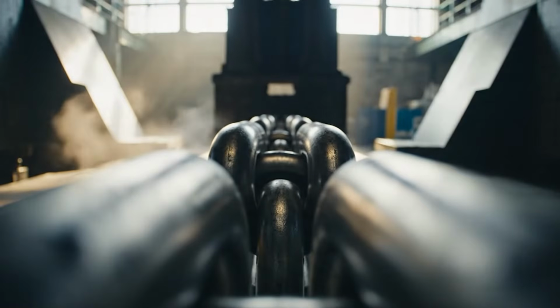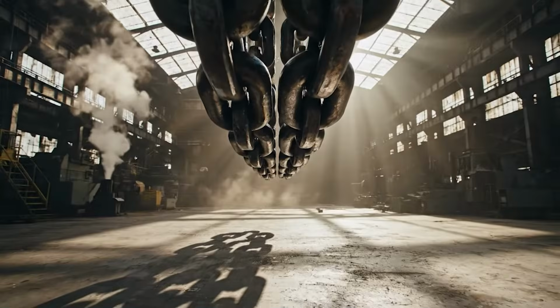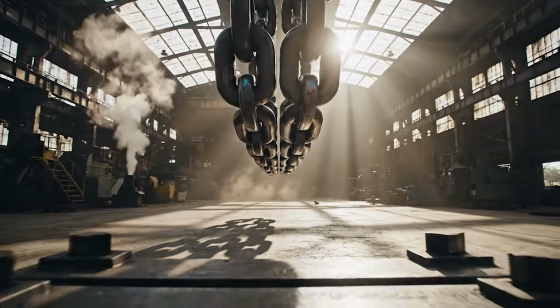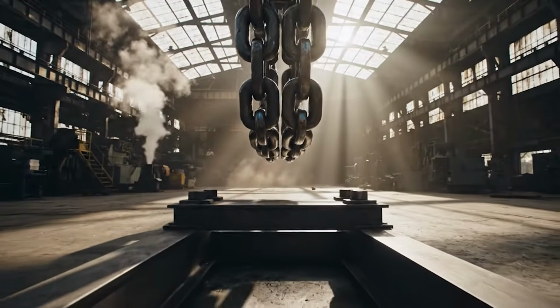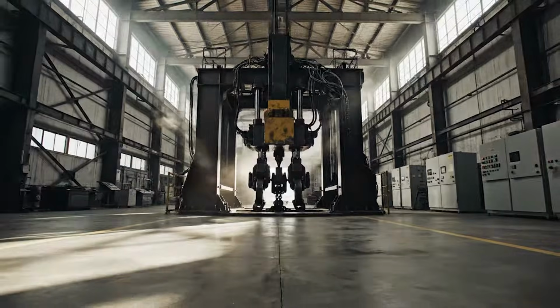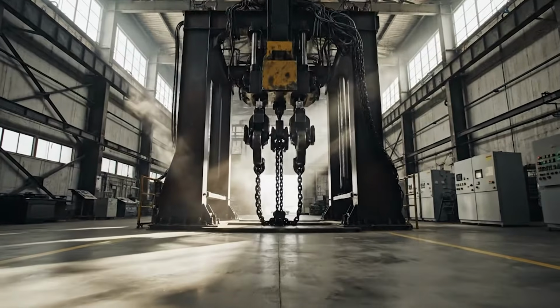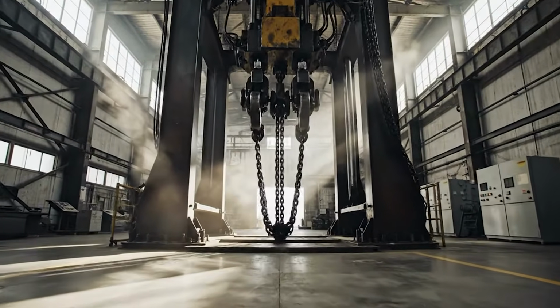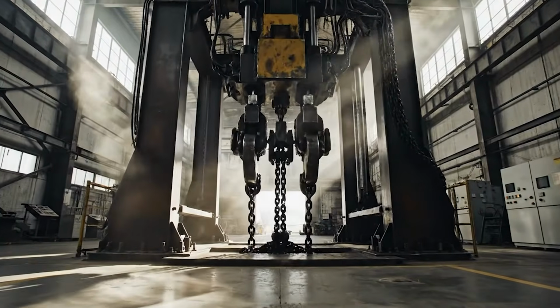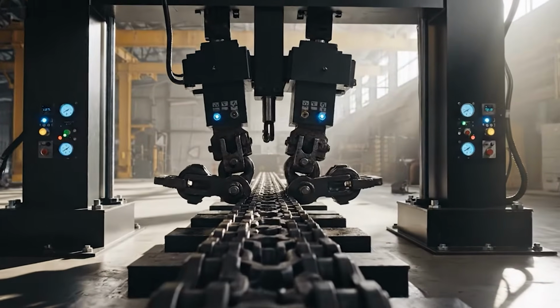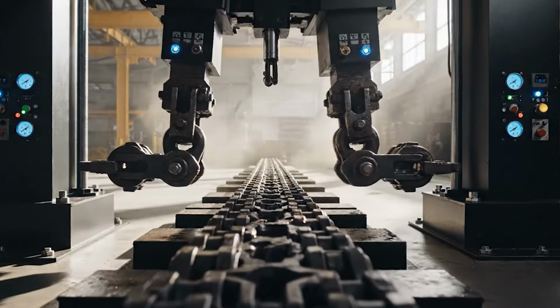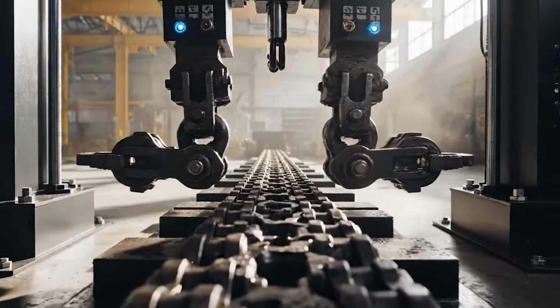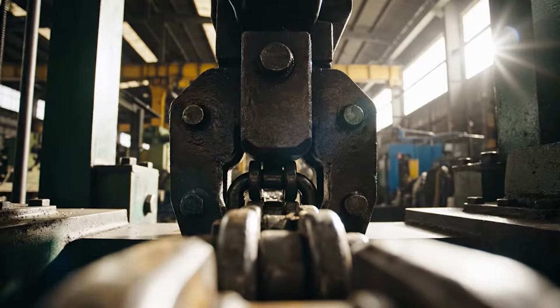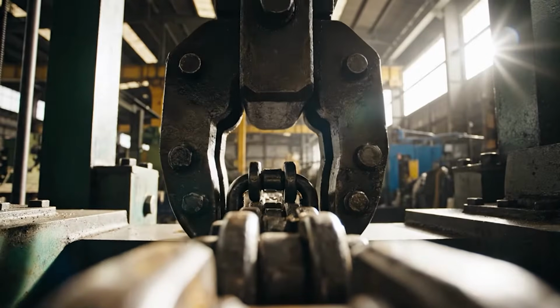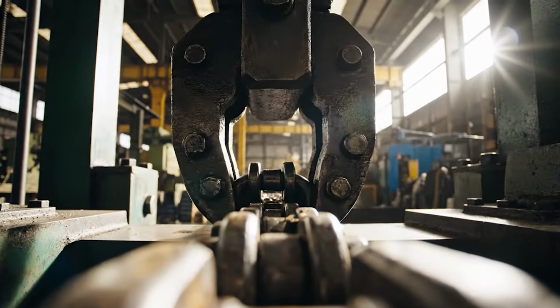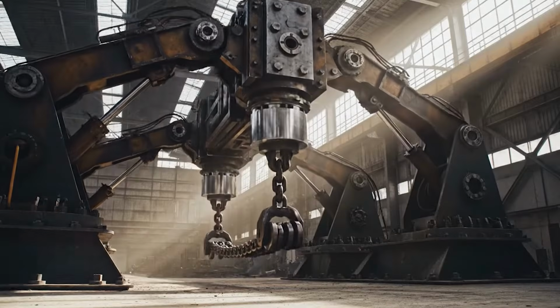Now comes the moment of truth. The chain is clamped between giant hydraulic arms. The machine begins to pull 5 tons, 10 tons, 50 tons, depending on the chain's rated strength. The metal stretches microscopically, and sensors track every change. A certified industrial chain must survive a load 2 to 3 times higher than anything it will ever face in real operation. If a link elongates too much, if a weld shows microscopic cracks, if the grain structure fails, the test ends immediately. The entire batch is rejected. But the chains that pass, they earn their place in the world's harshest environments.